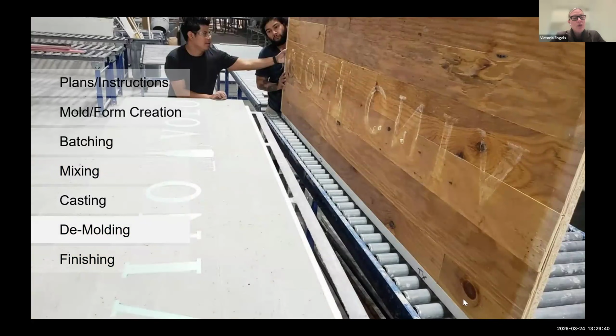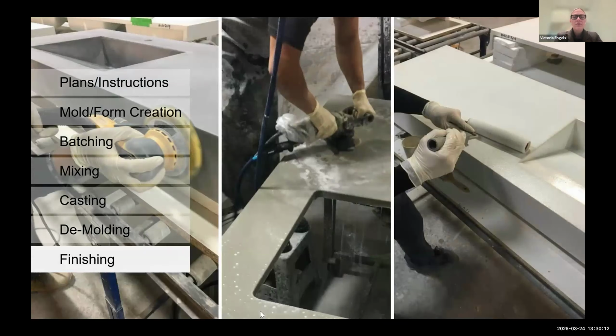Once the concrete has cured to the manufacturer's protocols, the concrete must be removed from the forms. The curing process can take from 3 hours to 3 days, depending on the mix design, the application, the minimum strength of the concrete, and also it needs to be safely removed from the forms. Fabricators are going to take precautions while demolding so they don't damage both the concrete piece or the forms that they're working with in case they need to be reused.